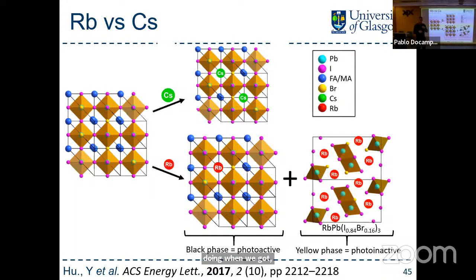We normally work with a mixture of bromide and iodide. It turns out that it's more thermodynamically favorable to form a rubidium-lead bromide side phase. So we leach out some of those ions from the perovskite structure. So now it's more iodide rich, so the structure is bigger.